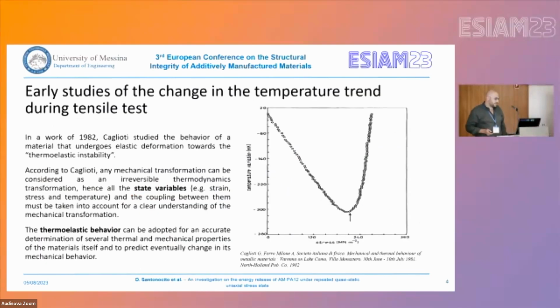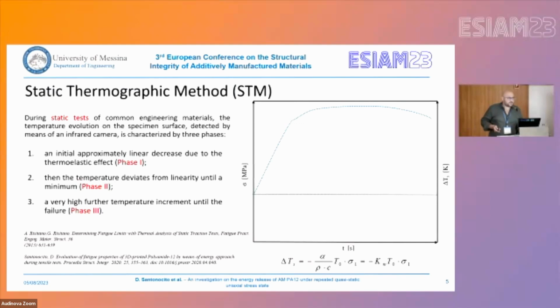Another idea comes from a previous work of Caglioti, where the temperature trend during a static tensile test was observed with a thermocamera, observing a first part of linear decrement if I put the material in tension. Moving from this assumption, Risitano proposed the static thermographic method to assess the first damage that I can introduce in the material if I stress it.